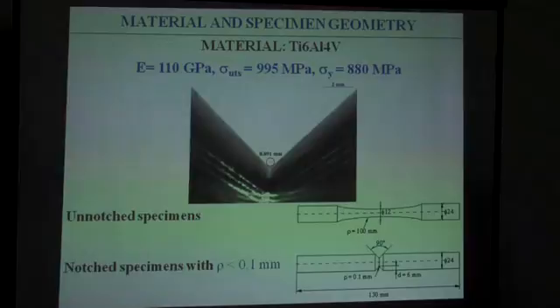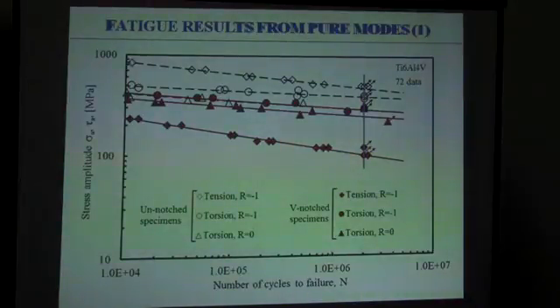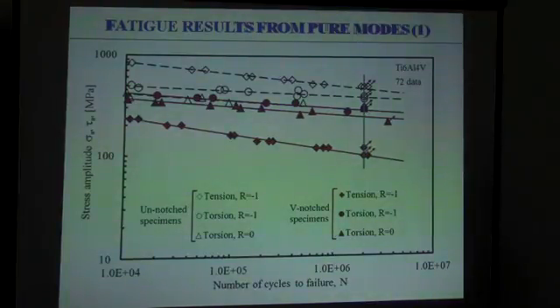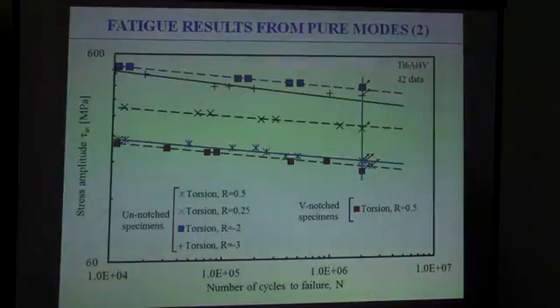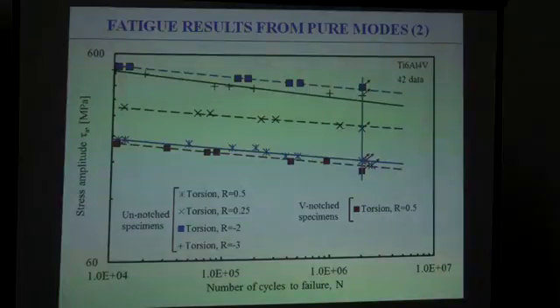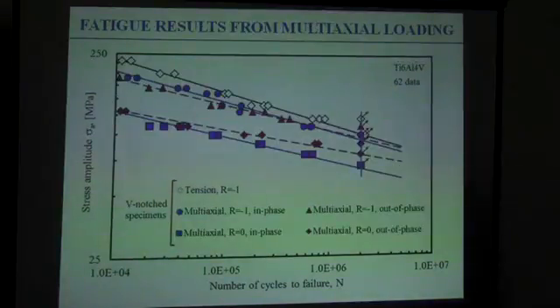After that, we have collected data for different loading cases, and in particular, we have considered pure tension and pure torsion cases with sharp notched specimens and blunt notched specimens. After that, we have changed, for example under torsion, the load ratio from -3 to 0.5, and we have seen that there is a very strong effect of this nominal load ratio also under torsion loading for this material.